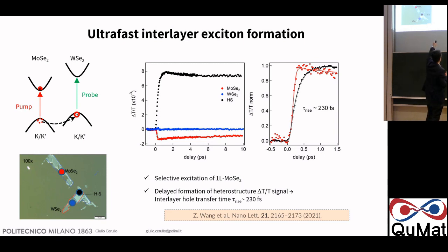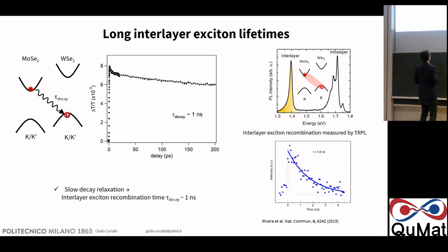But now, if we pump the heterostructure, we see a very strong signal, which is a bleaching, and this bleaching is clearly delayed by a rise time of about 230 femtoseconds. So we really resolve the interlayer hole transfer process with a time constant on the order of 230 femtoseconds. Now, we can also look at the recombination time, which is much longer than in the case of the normal intralayer exciton. It is on the order of 1 nanosecond.